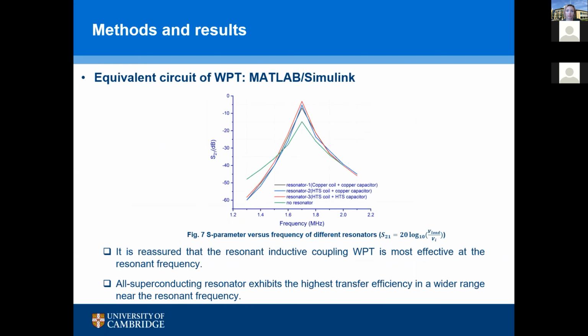Furthermore, we curved the transfer function expressed as a scattering parameter, namely the S parameter, for different combinations in the resonance. It is very sure that the resonant inductive coupling WPT system is most effective at the resonant frequency. Also, the all superconducting resonator exhibits the highest transfer efficiency in a wide range near the resonant frequency, which is likely to benefit the tuning process of a WPT system.